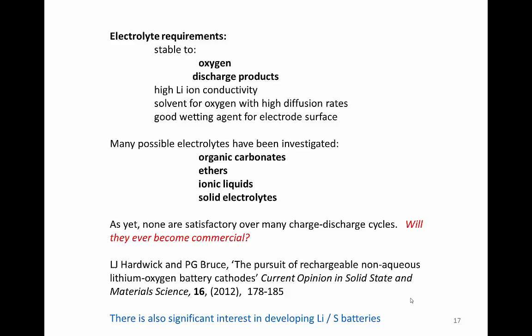And the electrolyte requirements, they need to be stable in contact with oxygen and with the discharge products. We need to have high lithium ion conductivity. We need a solvent for oxygen with high diffusion rates, and good wetting so that the reactions which occur at the electrode surfaces are rapid. So many possible electrolytes have been investigated, various organic salts, organic carbonates, and ethers, ionic liquids, and solid electrolytes. So many materials have been considered, but as yet none of them are satisfactory and give good performance over many charge-discharge cycles. So you will see in the literature lots of papers where people report results, but generally the cycling is pretty limited. And so there is the question whether they will ever become commercial.